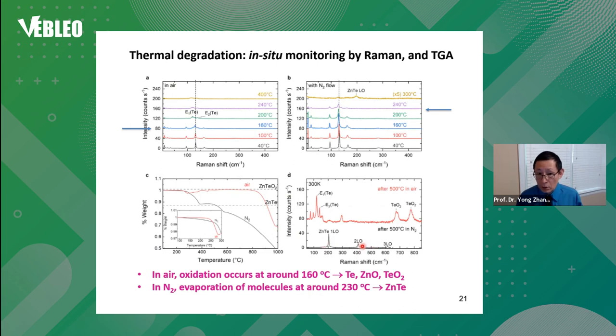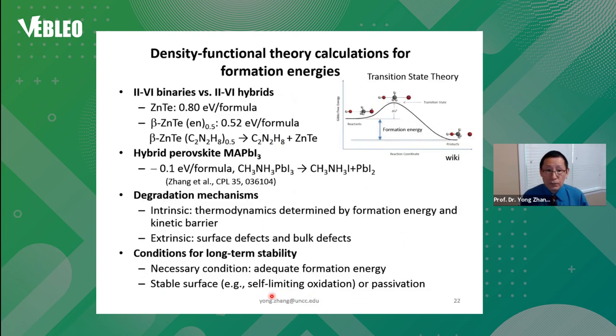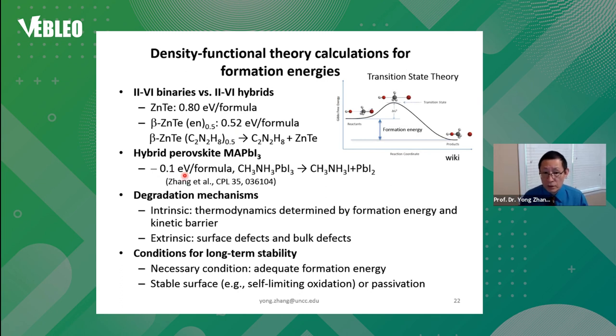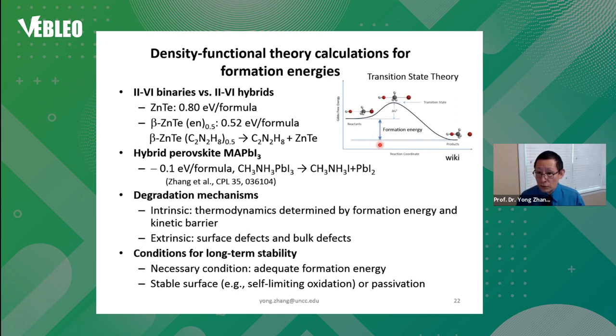I want to mention the density functional theory calculations. The calculated formation energy of zinc telluride is about 0.8 eV, but for the hybrid it is about 0.5 eV — less than a factor of two reduction. However, for hybrid perovskite the calculation gives minus 0.1 eV, indicating a spontaneously unstable structure. This can be explained by transition state theory for chemical reactions: a larger formation energy tends to give more intrinsic stability; however, you could have a metastable state if there is some kinetic barrier — that is probably the case for hybrid perovskite.